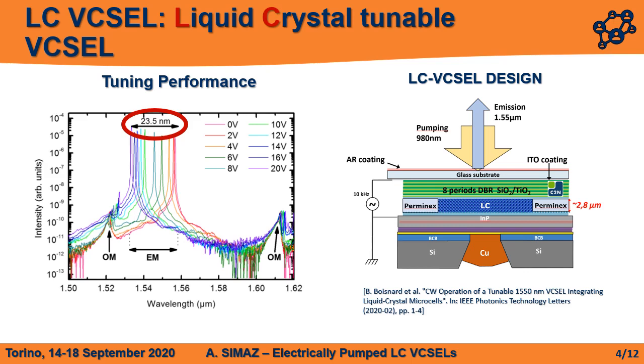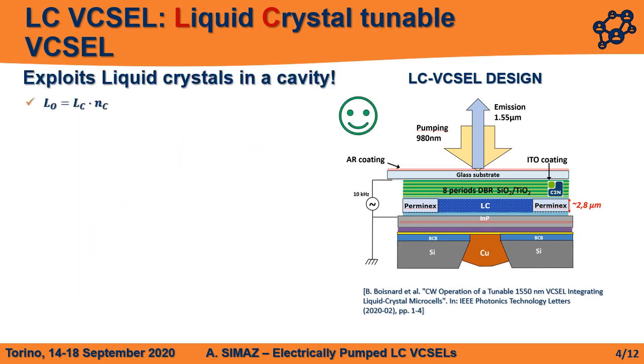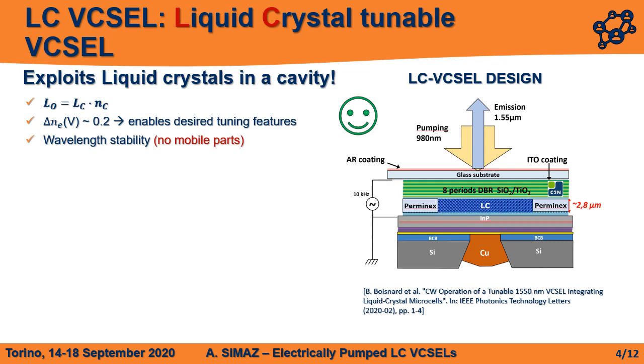Yes, indeed, and it comes from the liquid crystal VCSEL. Here on the right it is shown a first working prototype of an optically pumped liquid crystal VCSEL, with a tuning range of 23.5 nm at 20 volts applied. The basic principle of a liquid crystal VCSEL is to change the optical length by varying the refractive index of the material inside the cavity, instead of varying the cavity length. For this reason, we use an anisotropic material such as the liquid crystal. The extraordinary refractive index varies by 0.2 and leads to a wavelength variation. This tuning range depends on the geometry of the structure and the type of the liquid crystal. Moreover, the structure presents no mobile parts, which makes the emission wavelength very stable.